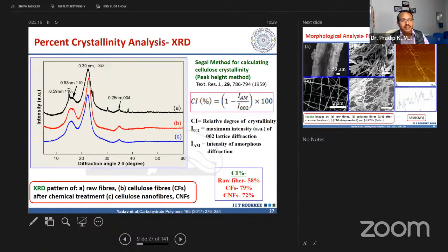We have done the percent crystallinity calculation in the cellulose nanofiber. It is not cellulose nanocrystal. If it's cellulose nanocrystal, we get more than 95% crystallinity. But for cellulose fiber, we are getting 79% crystallinity. After reprocessing cellulose to get cellulose nanofiber, we are getting a reduction of the crystallinity to 72%, because whenever we apply ultrasonication, it is breaking the cellulose fiber. As a result, there is a little bit of reduction of the crystallinity.